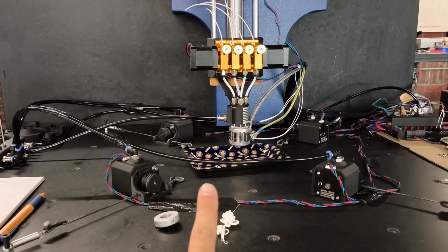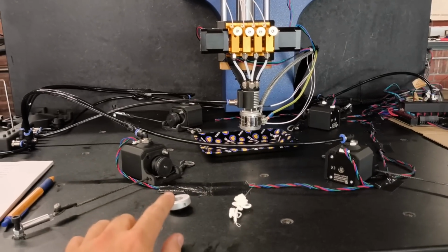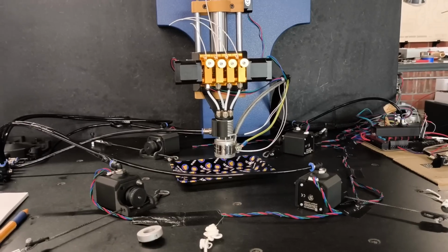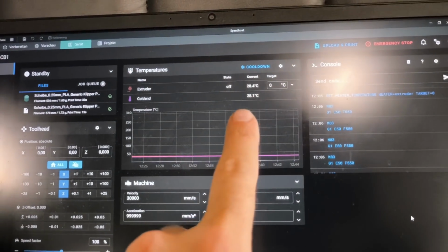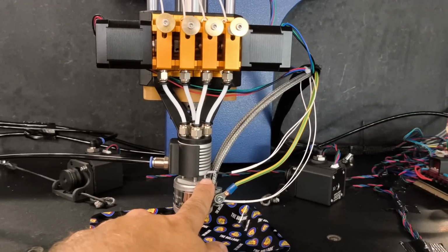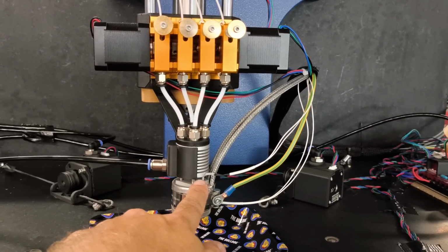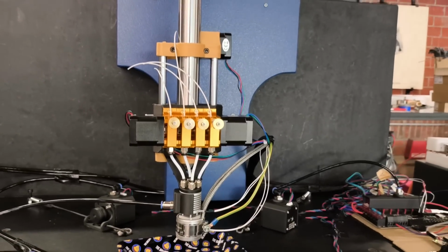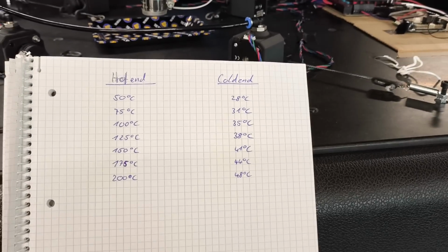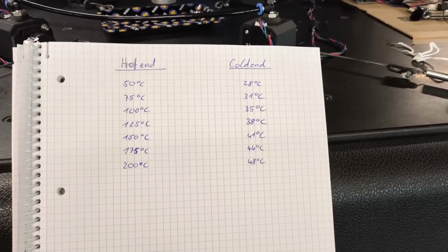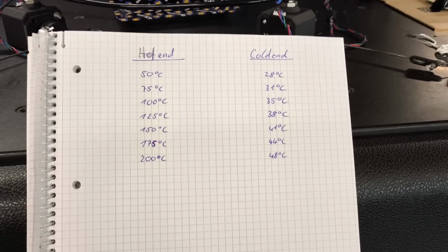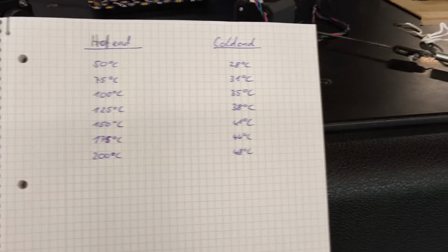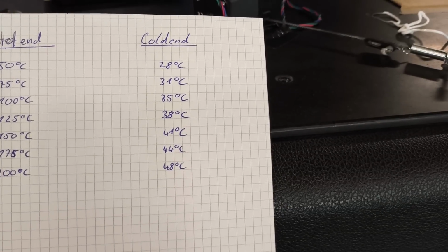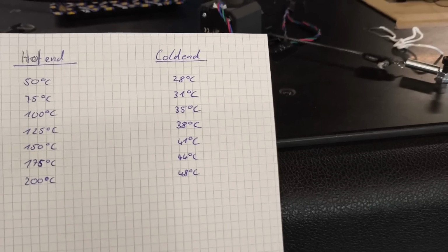Yeah, so we went with the first extrusion without a nozzle, and we're gonna continue that just for setting everything up. As you can see in Klipper, I added the second thermistor, which is sitting up here in the cold end. So this is like the first position of the cold end, and I already have done some heat testing. Left side is hot end temperature, right side is cold end temperature, and as you can see, by increasing temperature by 25 degrees C, it will increase temperature by 3 to 4 degrees on the cold end side.